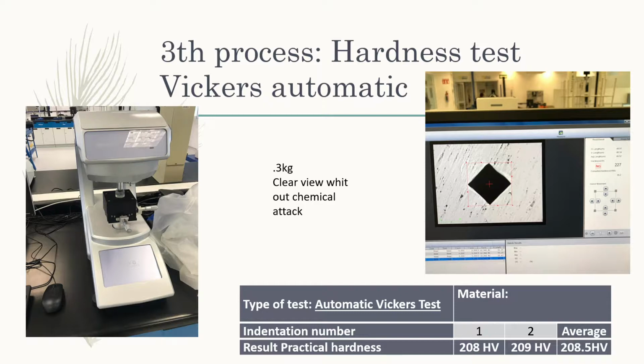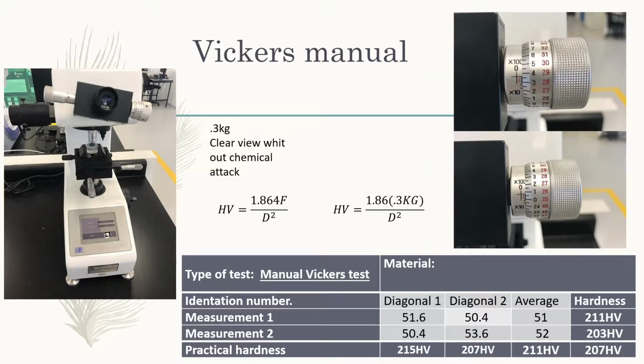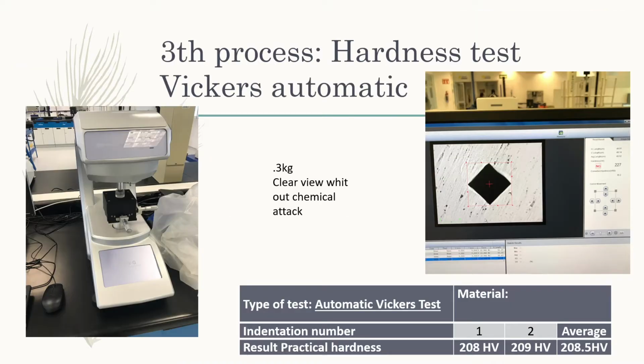The next process is the hardness tests, all the hardness tests. The first one was the Vickers automatic. We do it 2 times and we get an average of 208.5 HV. Next we do the Vickers manual to compare it with the automatic, and we do it 2 times and we get a practical hardness of 207 HV. So it's not very different from the Vickers automatic.